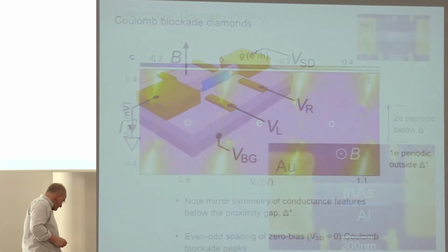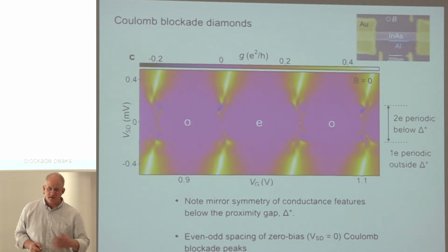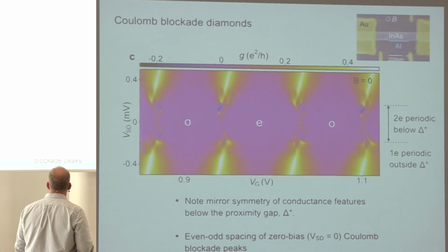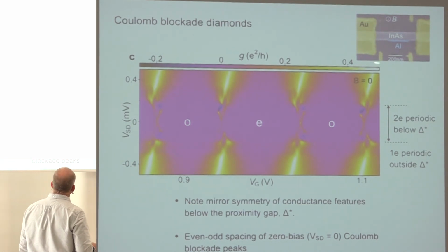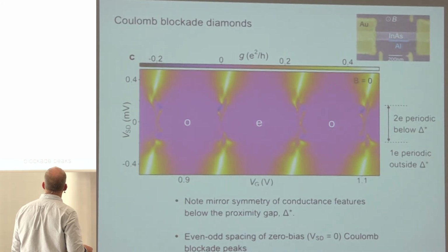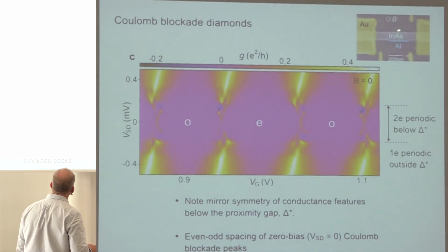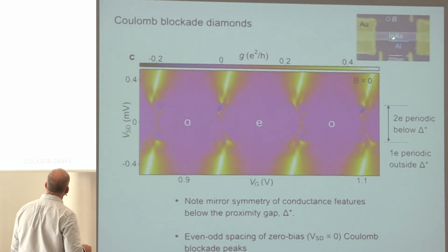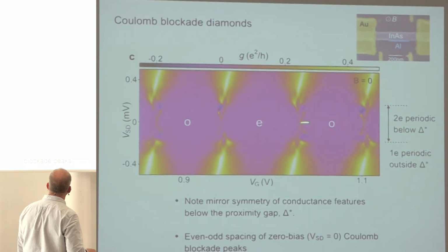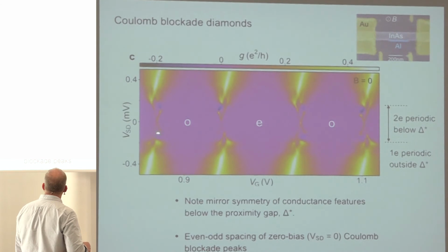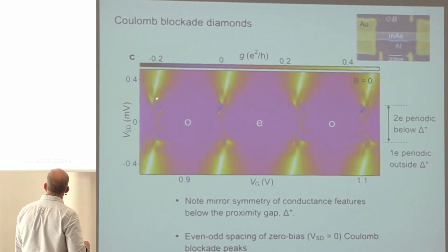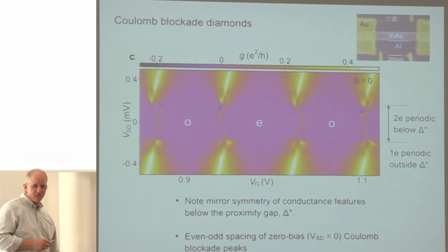It's a different geometry than we saw before, but one that also can shed some light on what are the electronic states that live within the device. When we study this thing as if it was a Coulomb blockaded island, we see interesting conduction patterns, and I'll tell you about those for now. Because electrons can only enter this small capacitance island when the electronic state of the next electron is available at the Fermi energy, you see these periodic conduction peaks, which are the familiar Coulomb blockade at zero bias. But at finite bias, you see something much more interesting in this device, something which I would say has never been seen before.